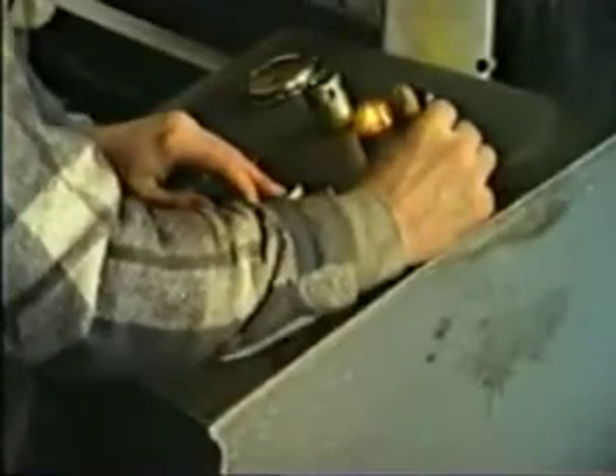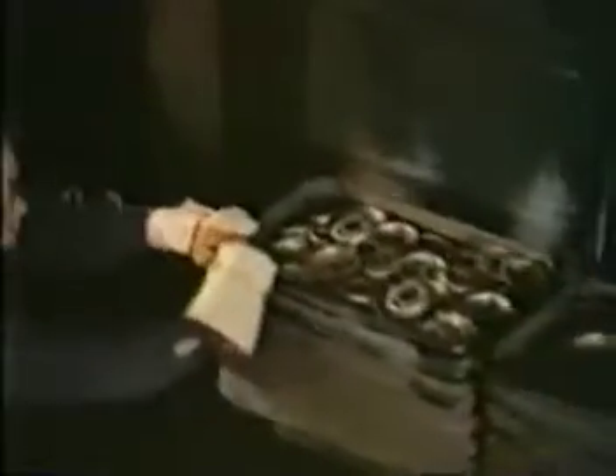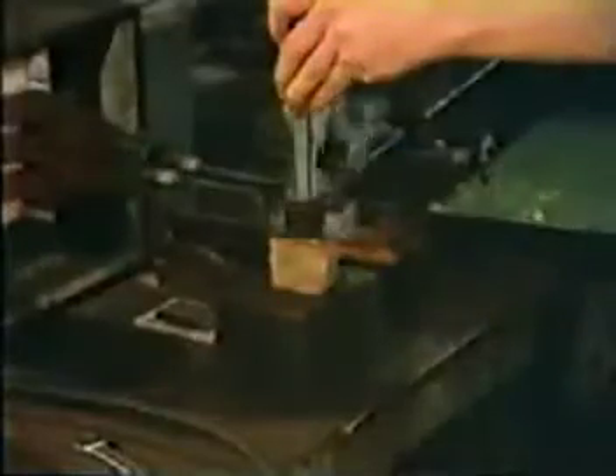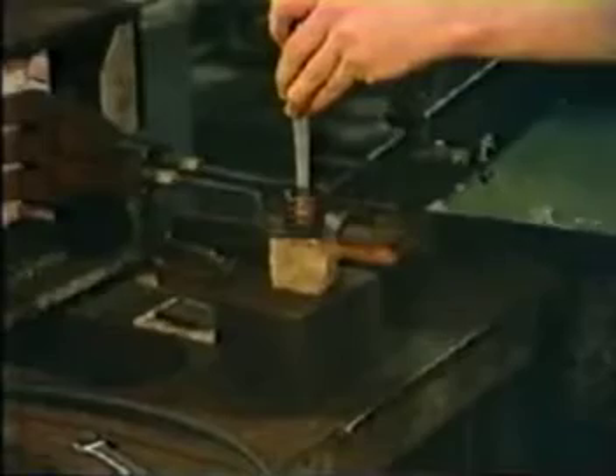Operation of an integral quench furnace can be practically automatic through the use of timers and other controls, requiring only that the work container be manually loaded into the furnace at the start of the processing cycle and transferred to the vestibule elevator for quenching at the end of the cycle. This equipment is generally used to process batches of work that can be loaded or fixtured in processing containers as shown here. Still, other examples of batch equipment include both high and low temperature molten salt baths and induction and flame heating, which use specially designed electrical coils or gas burner heads to apply heat selectively to the parts before they are quenched. The second category of equipment is the continuous furnace line used for heat treating large quantities of identical parts.